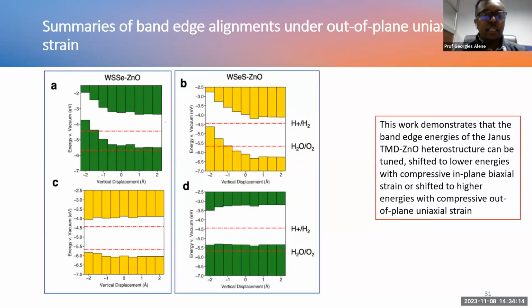We have also investigated the effect of uniaxial strain. By reducing the interlayer spacing between the monolayers for the heterostructure, and by stretching it, that means by increasing the interlayer spacing, we have tried to investigate the effect for photocatalytic activity. So we plotted the band edge together with the redox potential of water. And we have investigated different effects.